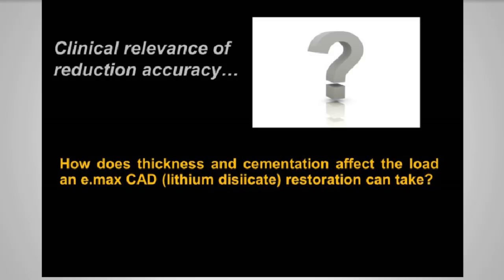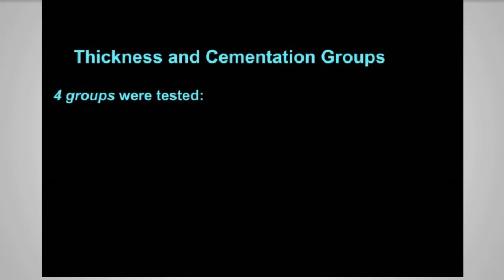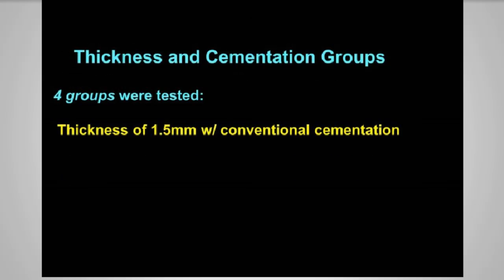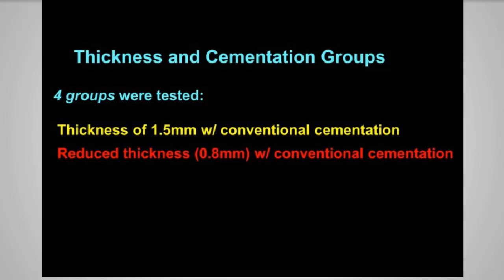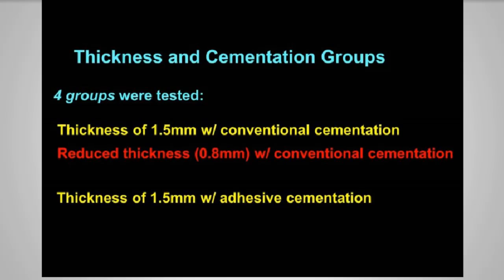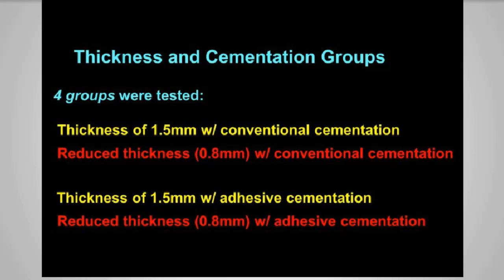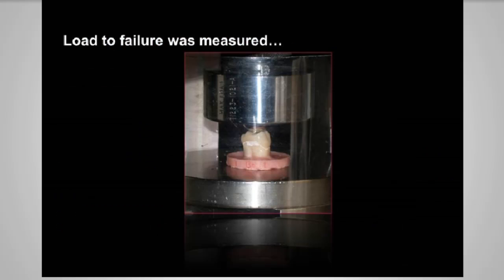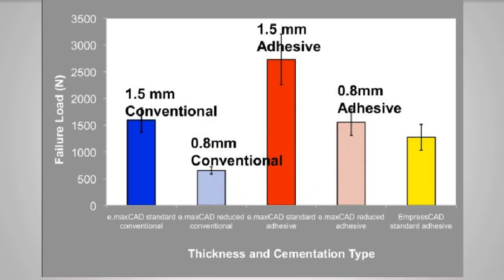If we look back up to lithium disilicate, how much load can it take? And this was an excellent study done. It was, I think, paid for by Ivoclar Vivadent on their lithium disilicate material e.max. 4 groups were tested: thickness of 1.5 millimeter with conventional cement, reduced thickness, and then thickness of 1.5 millimeters with adhesive cement, and then the same cement used in a reduced thickness. Load to failure was measured, and this is the result.